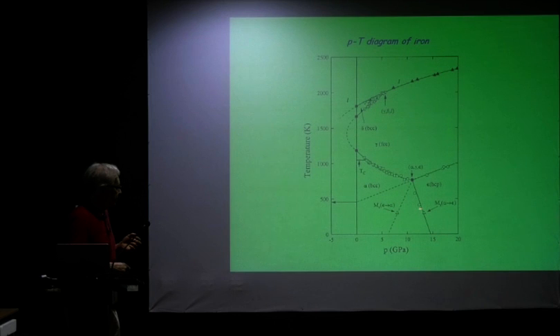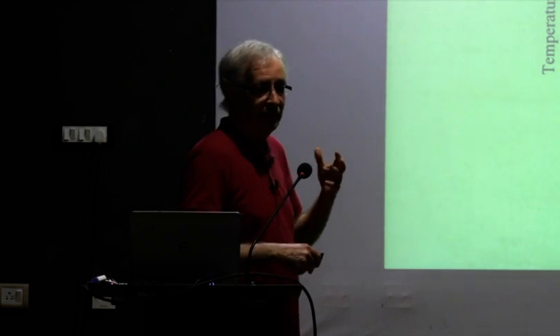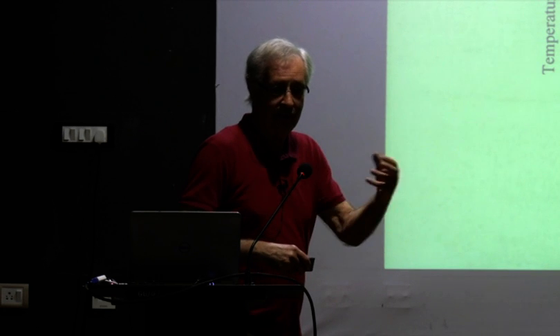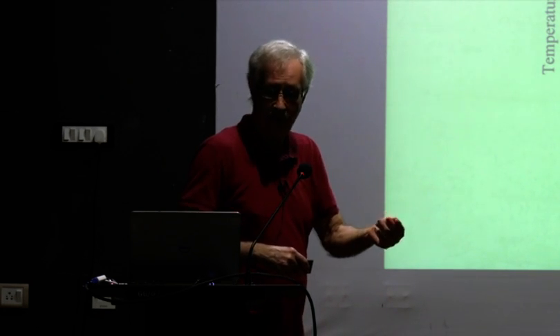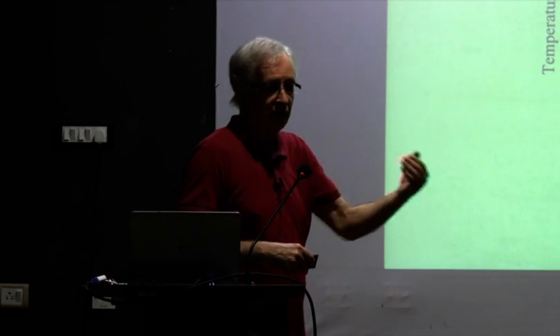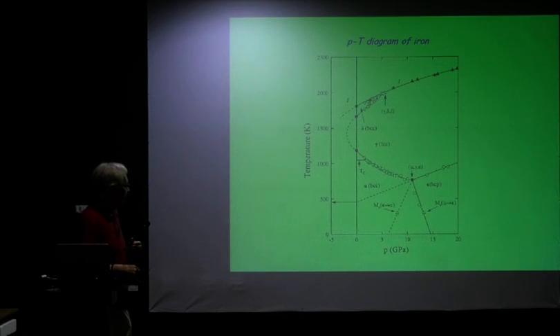These are designated as MS here and MS here in both cases. This is a mixed phase. It's like a martensitic transition undergoing, like in nickel titanium. You're applying a strain, you're inducing a martensitic transition. It's a martensitic-like transition going to the epsilon phase, and when you're coming back, you come through it with a hysteresis.